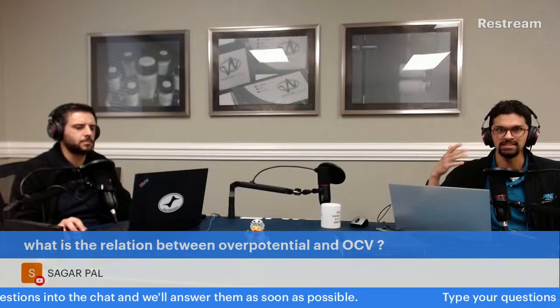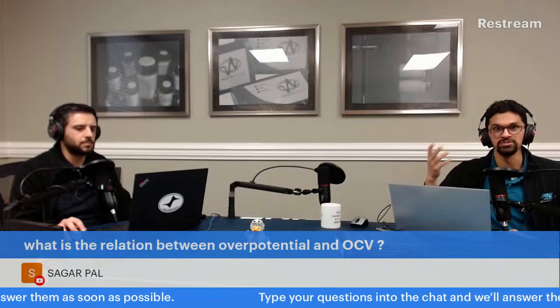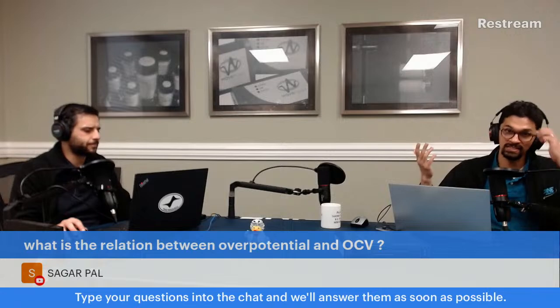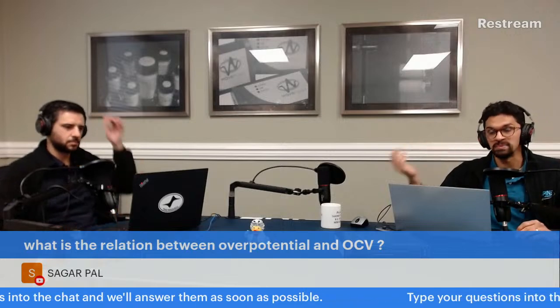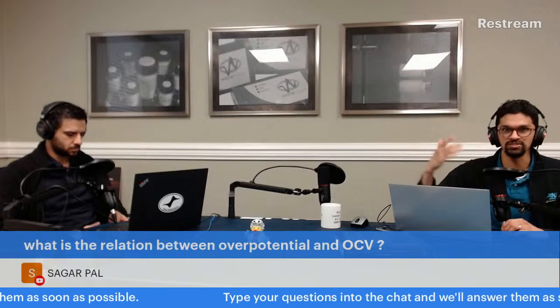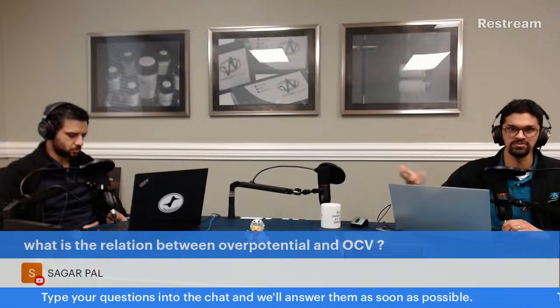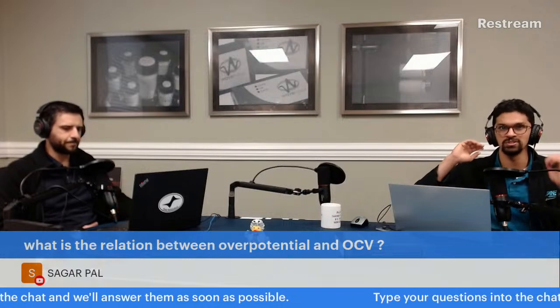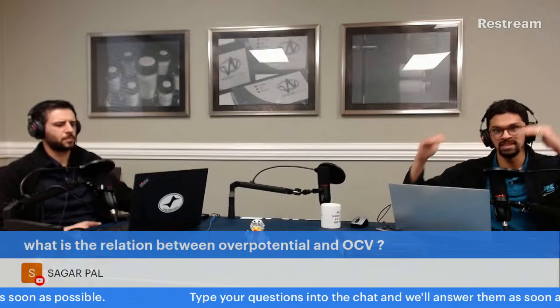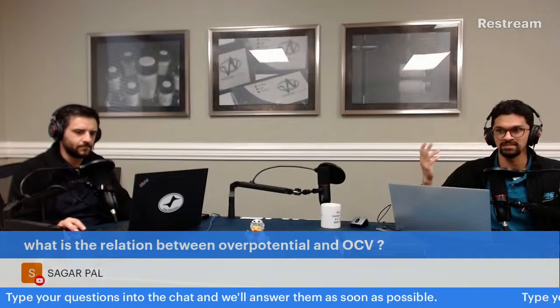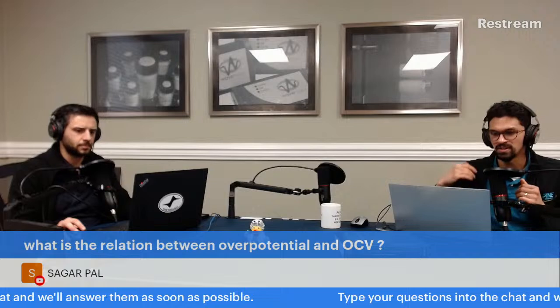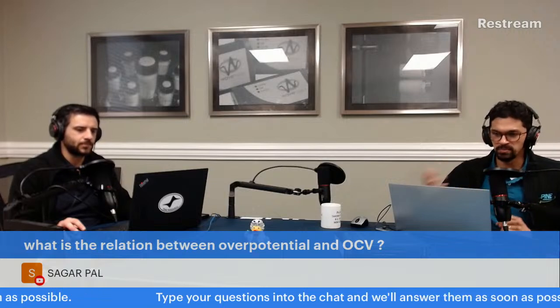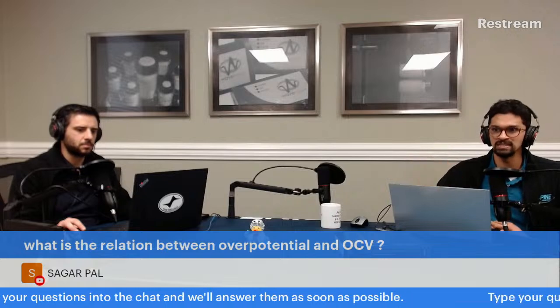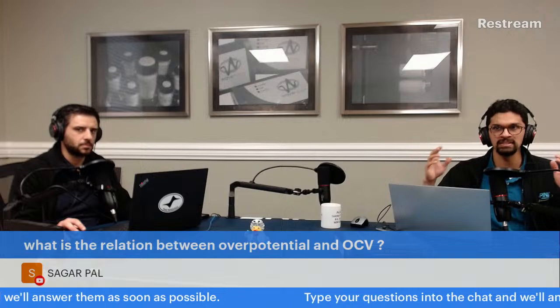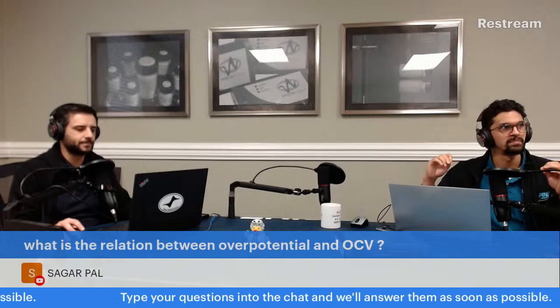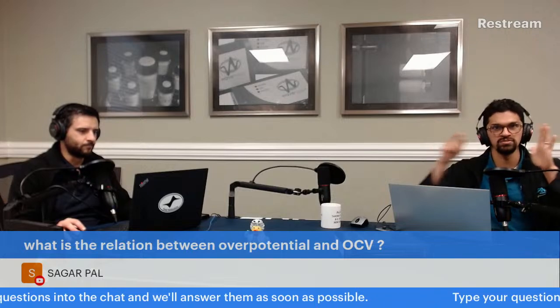Overpotential is used a lot in the catalysis field, usually to describe whether my material is more catalytically active or not. It may not be very active because the overpotential is super high. I need to apply an extra 300 or 500 millivolts to get the reaction to occur, especially at the same level of current as something that isn't that material. So that's how I think about overpotential. Open circuit voltage is something we talked about a little bit earlier. It's the voltage of the cell, just between these two points.